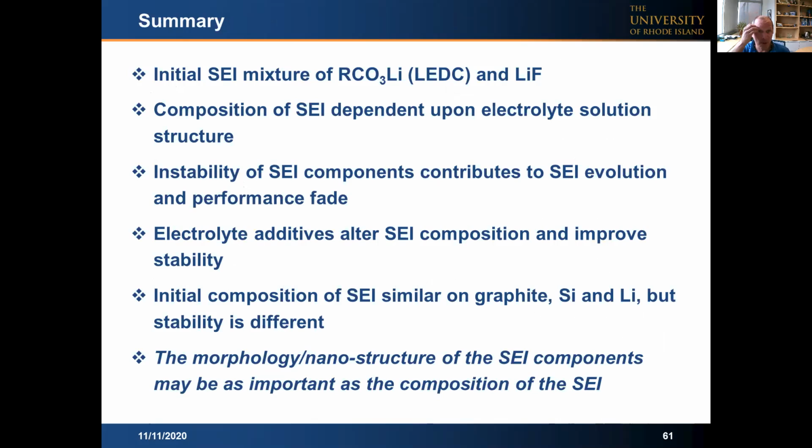So in summary, the initial SEI is a mixture of lithium ethylene dicarbonate for graphite anodes with LiPF6 and EC-based electrolytes. The initial SEI is a mixture of lithium alkyl carbonates, such as lithium ethylene dicarbonate, and lithium fluoride. The composition of the SEI is dependent upon the electrolyte solution structure. So if you increase the salt concentration, you typically increase the concentration of lithium fluoride.